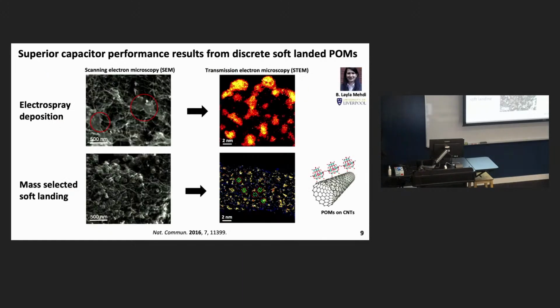So why is this? Well, to understand that, we needed some sort of spatially resolved characterization technique. So we started at relatively low spatial resolution using scanning electron microscopy, as shown on the left. On the top, I have the results for electrospray deposition, where you have full droplets reaching the surface. And on the bottom, I have the results for mass-selected ions, where only the discrete polyoxometalate reaches the surface. And you'll note here there's this sort of filamentaceous matter in these blue circles, which is not present when you do deposition of the mass-selected ion.